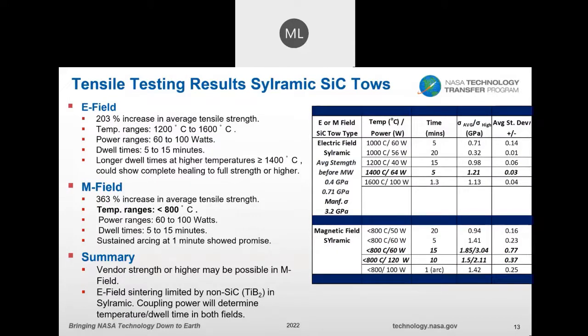So let's look at the results for the ceramic silicon carbide tows. What you'll see in this table is that we have a significant increase in the average tensile strength that we measured, compared to the measurements that we had, not the vendor measurements. The temperature ranged from 1200 to 1600 degrees. Power ranged from 60 to 100 watts. Dwell times from 5 to 15 minutes. And longer dwell times at higher temperatures exceeding 1400 degrees C showed complete healing to full strength or higher.